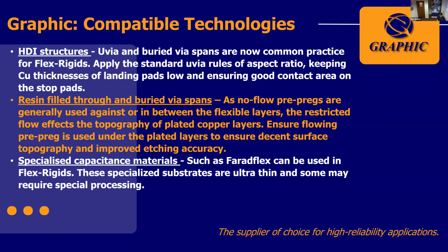Now, because we have a mixture of materials in flex rigids, you can get some distortion of the patterns as the pad stack is built up. So ensuring you have flowing pre-preg in the right areas does make sure that we have nice surface topography, which then allows for improved etching accuracy. Now, the no-flow pre-preg and the flowing pre-preg, it might be the same high Tg FR4 material. However, they will have differing bonding requirements. So you'll have a no-flow bond, and then you'll have a flowing pre-preg bond. So it might not be the case that you need to have the flowing pre-preg. If you do, then we do need to go through extra laminations, which does cost a lot more.